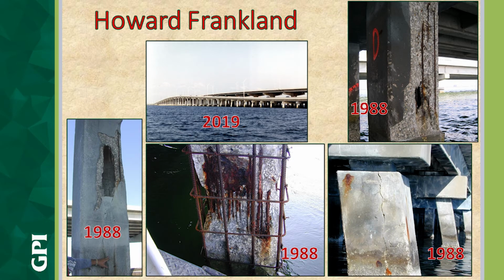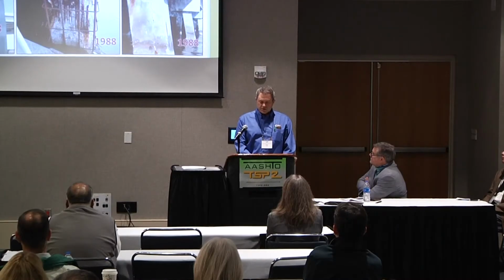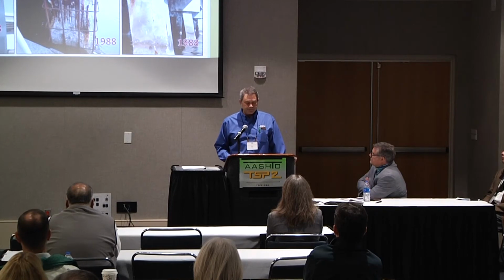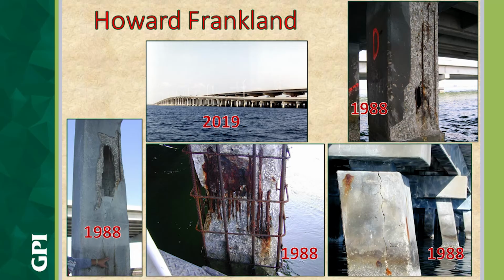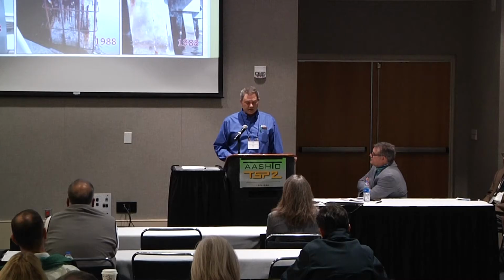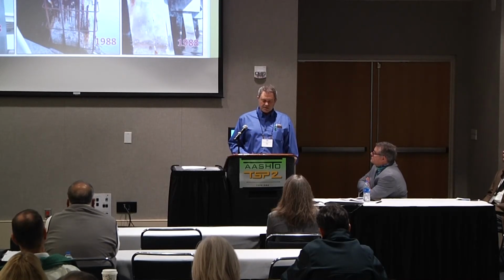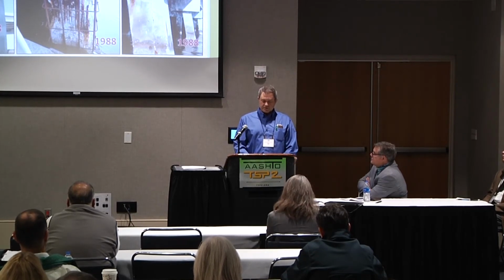The pictures depict the condition of the substructure in 1988 after 23 years of service. And just like Crescent Beach Bridge, the construction with low durability concrete, not enough cover, and exposure to a highly corrosive environment led to significant early life corrosion and substructure degradation. FDOT chose cathodic protection preservation rather than demolition and replacement. And again, like Crescent Beach, it is in full load service today.